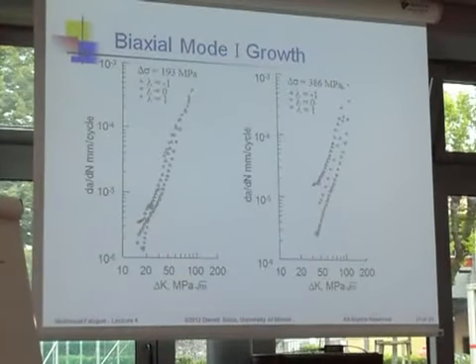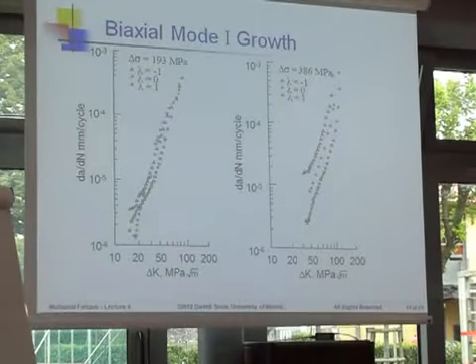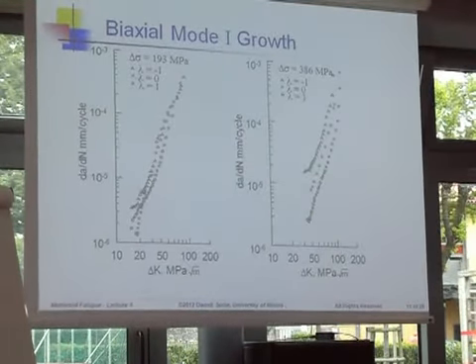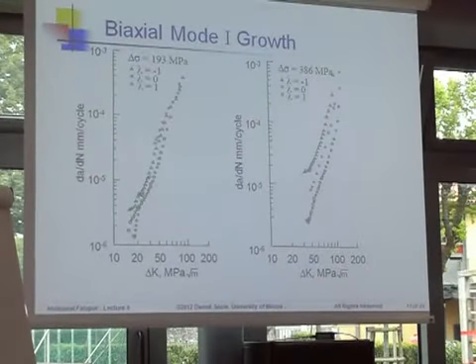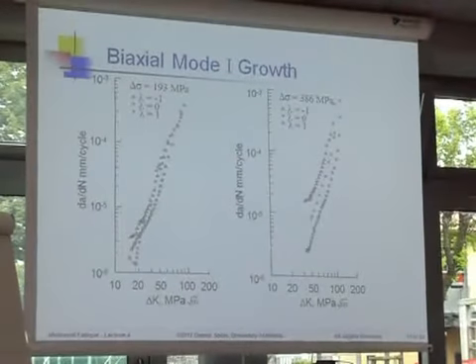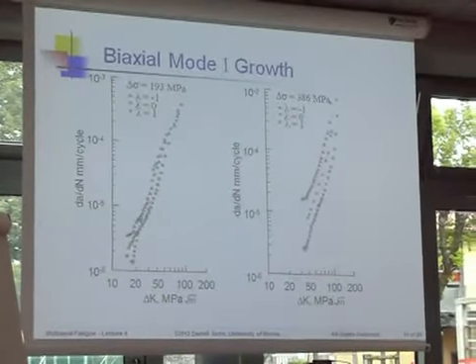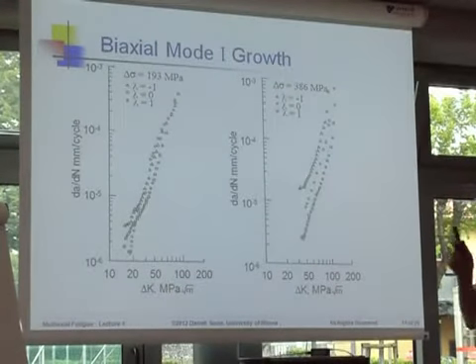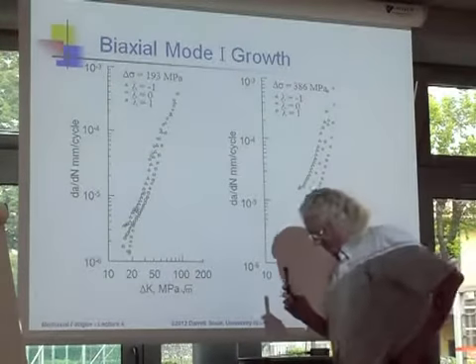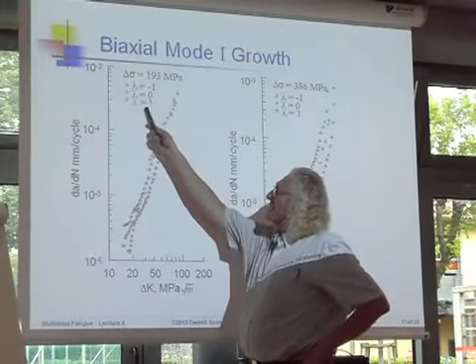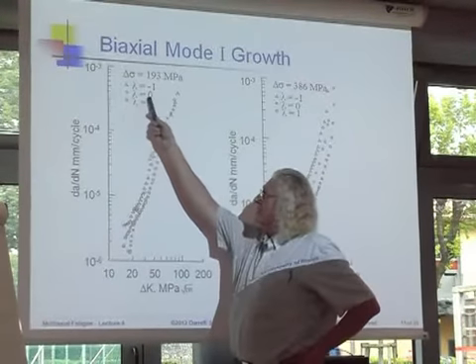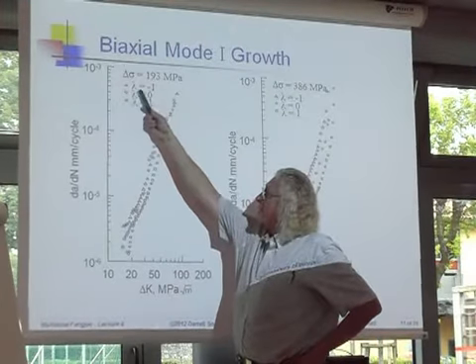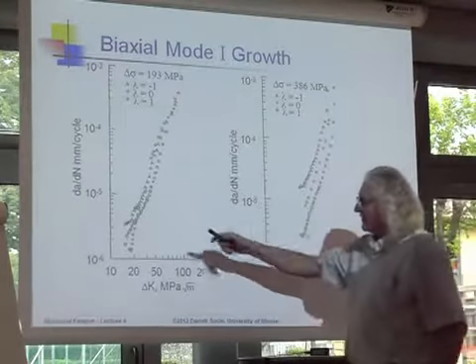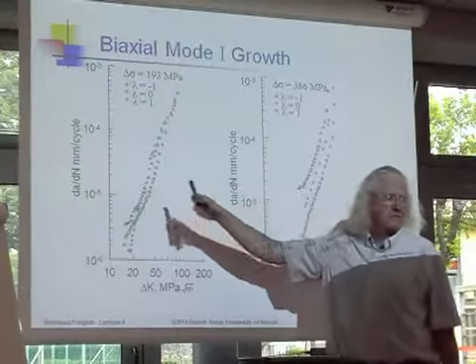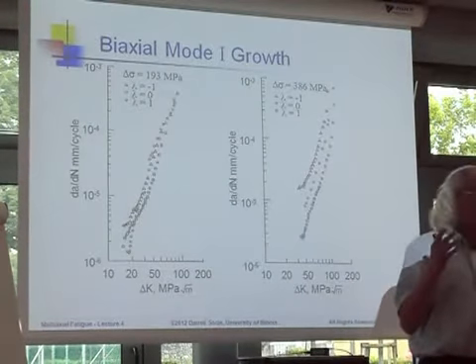Right? Now, if you go into literature, you will find that there is very little work on fatigue crack growth under the other modes of loading or any kind of combined loading. And one of the problems is illustrated here. So here's data about the growth of a mode 1 crack as you change the loading. And so lambda equals 1 is biaxial tension loading. Lambda equals 0 is uniaxial loading. And lambda equal -1 is the shear loading, but on a tension plane. And here's what the growth rates are under those 3 modes. Hardly any difference. Hardly any difference.